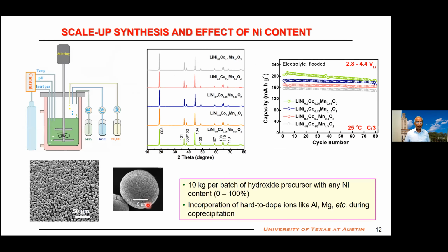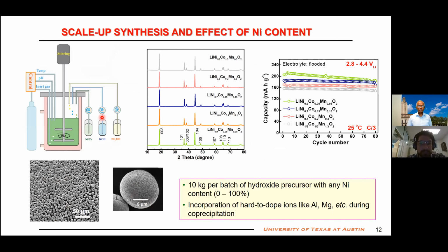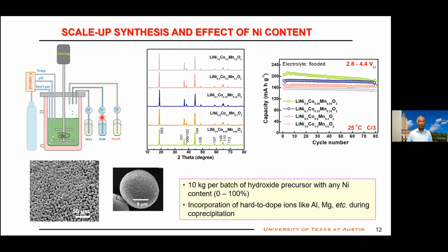So I want to mention 3 things important here. We have to make the materials in the right way, otherwise it will not be practically relevant. So we can make any particle size from 2 micron to 20 micron secondary particle size you see here. Normally we use 12 micron, similar to what the industry uses. We can make good material, we can scale up to 10 kilogram per batch. That's good. Next, we do our measurements in full cell with graphite anode, so the data are more reliable rather than having too much lithium on the anode side.